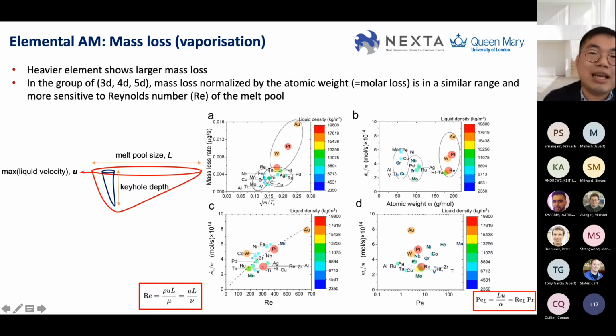And then we can see that it is chemistry dependent on the process, and then we can extract some trend of the mass loss. For example, heavier elements, larger mass loss. The trend actually has a relationship with the flow, which we can't extract using traditional FE simulation if we're not considering fluid flow, for example. And the trend in the diffusivity is not very clear, and that's why there's something called the Peclet number here.